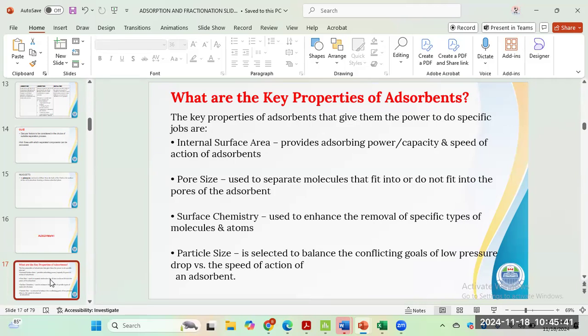So you have to study, if you are adsorbing gases or vapors, the chemistry between the adsorbate and the adsorbent. Very important. Then the particle size. When you have a smaller particle size, you are likely to have high pressure drops, and a larger particle size may lead to low pressure drops. So depending on the design of your process, you have to understand the particle size of the adsorbate itself and the adsorbent. Okay, so all these factors, from the topics I gave you, some of you will still be speaking more on them from a practical point of view.